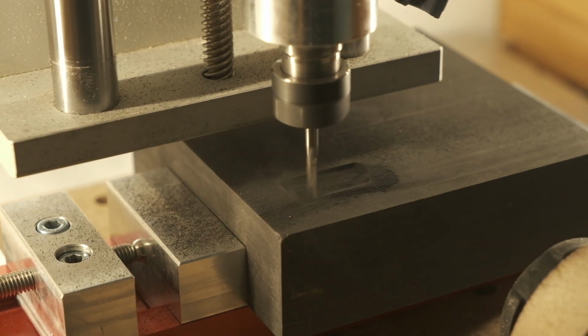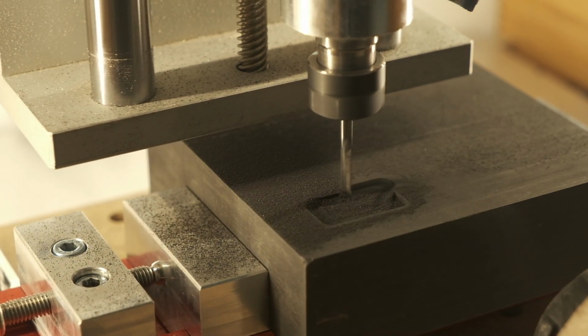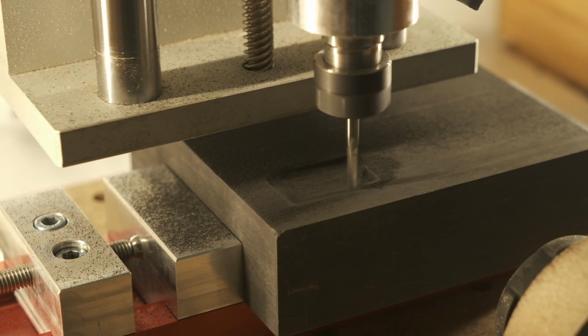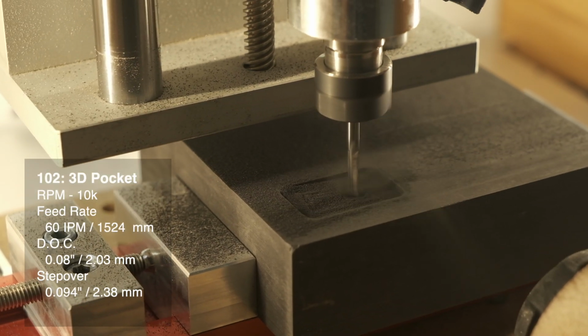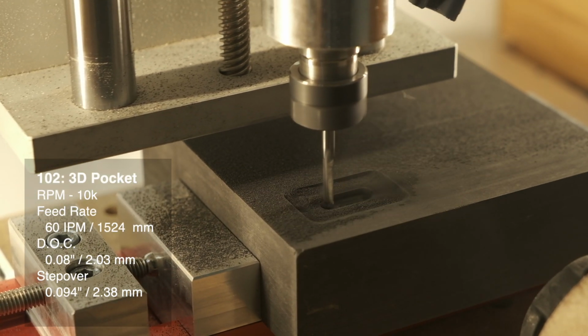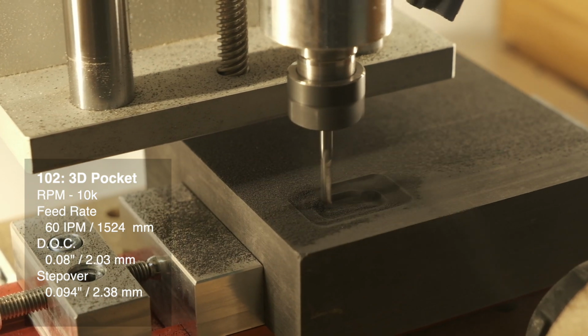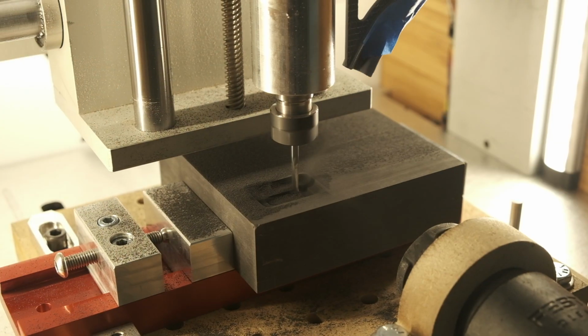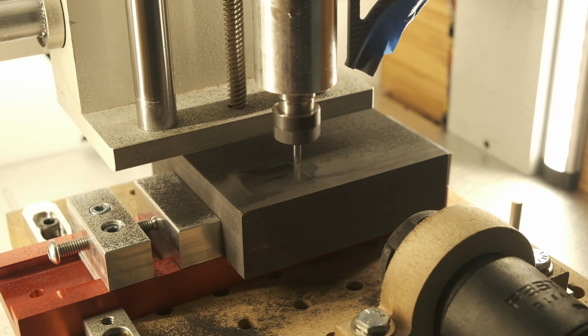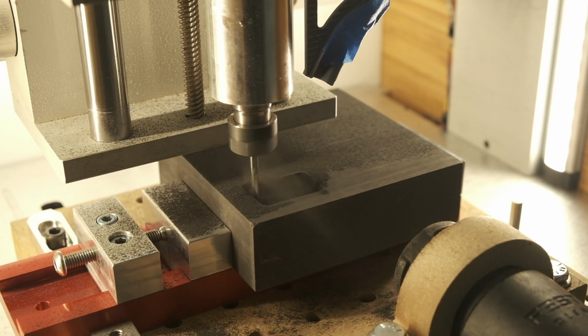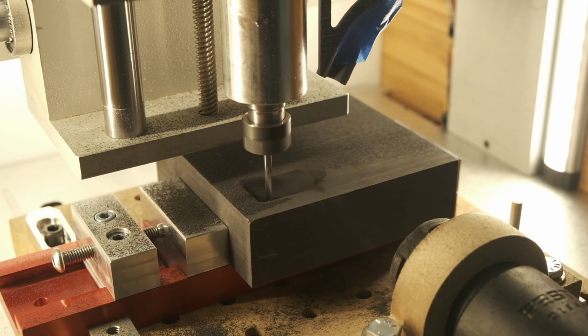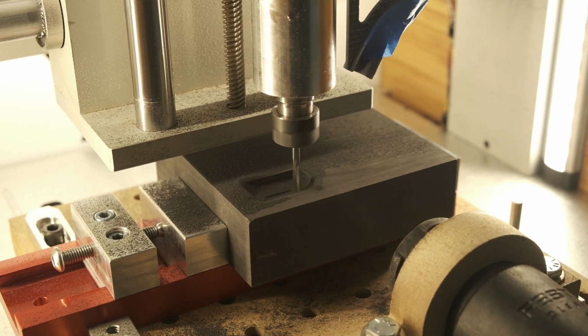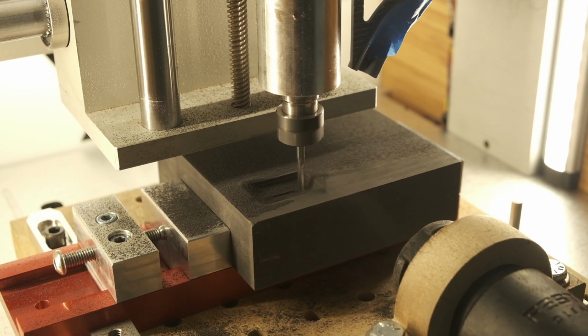Okay, so with that warning out of the way, here is the actual machining. Starting with the 1/8 inch end mill, I'm running at 10,000 RPM, a 60 inch per minute feed rate, a 0.08 inch depth of cut, and a step over of up to 75%. Because I was uncertain of how graphite would shear or if it would chip out with such aggressive parameters, I left my radial stock to leave pretty high at 0.02 inches. These parameters ended up working just fine.